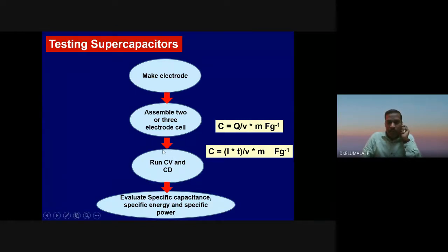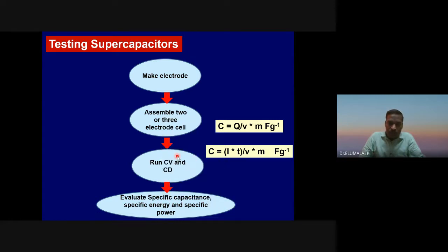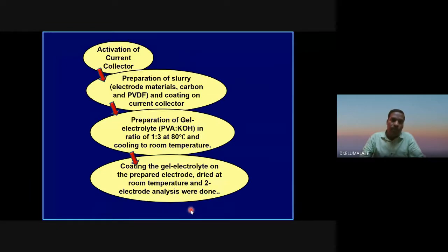Yeah, so the device will have 2 electrodes and all the fundamentals you can do with a 3 electrode system. So this point: many people mistakenly estimate the energy density and power density from the 3 electrode system. And many good papers are also published. I don't agree with that. This has been going on for the last 10 years, but now people are changing. Estimation of energy density and power density is appropriate if you use the device, that is, a 2 electrode system.